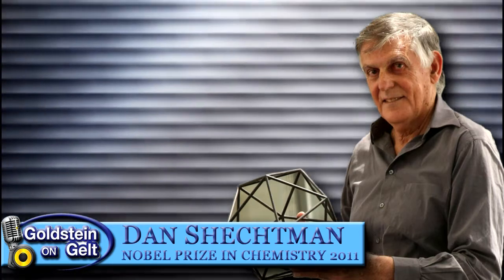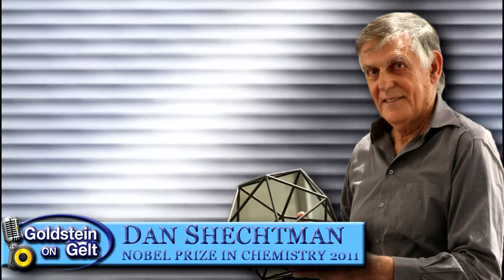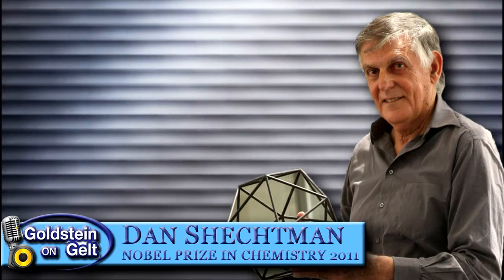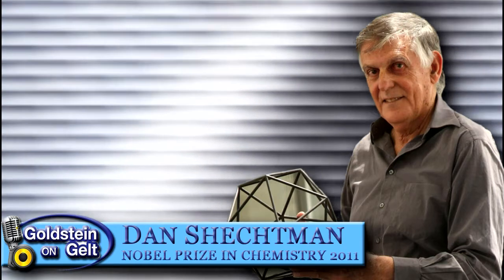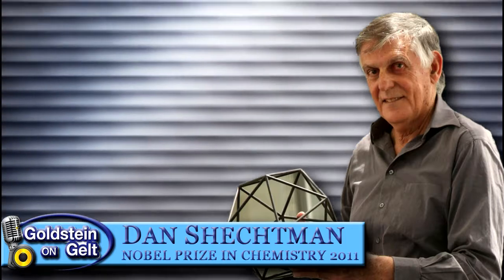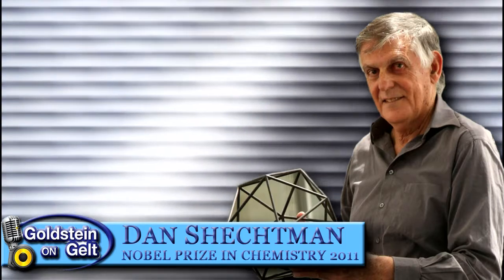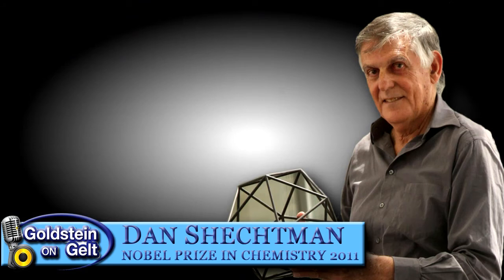They use it in operation rooms, in surgeries, and so on. Any part, if you need a steel to touch the body, outside or inside, this is a very good steel to use. And then there are many other applications. So what's special about this steel? What is special is that this steel is strengthened by tiny little particles which are quasicrystalline, which are embedded in the steel, and this makes the steel very interesting and very useful for many applications.